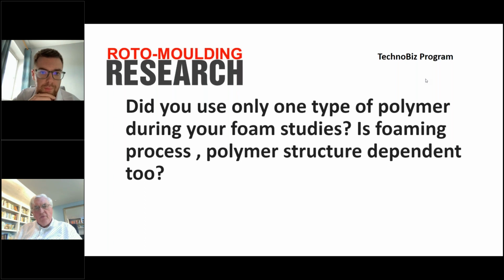What about the melt flows of the polyethylene we're using? Did you try different melt flow materials? I did, yeah. So I had a series of LDPE materials that were all roughly the same. They all came from the same brand name. I think they were Lotrene materials, and the MFI was between 0.8 and 70. And I used that then to explain the effects of rheology on the foams produced.